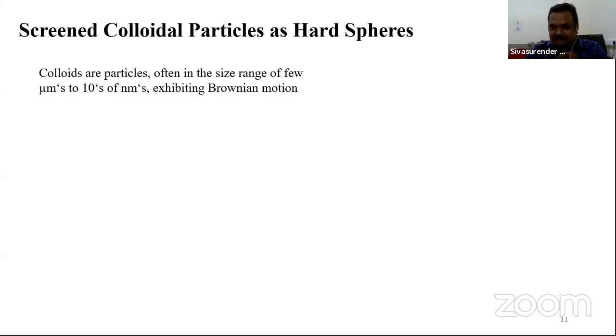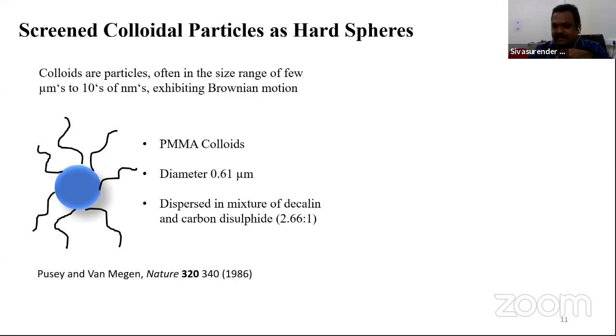And with these simple systems, Pusey and van Megen in 1986 came up with a simple system. These are simple polymer-based colloids, and their diameters are of the order of 600 nanometers. They dispersed these colloids in a solvent which is a mixture of decalin and carbon disulfide. And they have some polymers which are grafted, as I've shown you with the black lines here. These are center PMMA colloids, and on top of that you have polymers which are grafted, and that minimizes the interaction. And then they could show that the interaction between two colloids is completely zero the moment they are completely separated, right? And hence they could create a hard sphere from an experimental perspective.